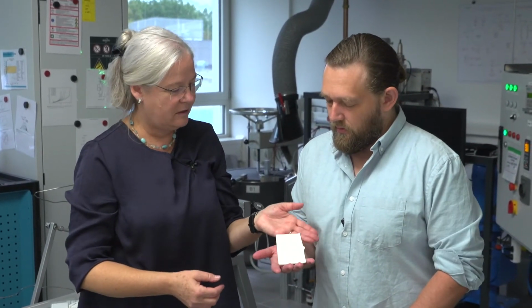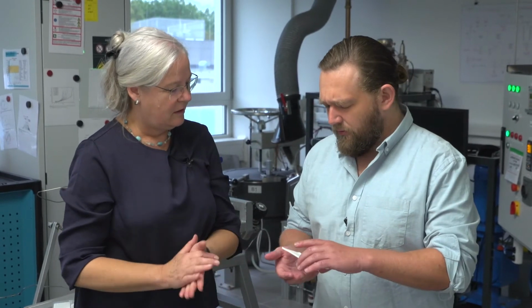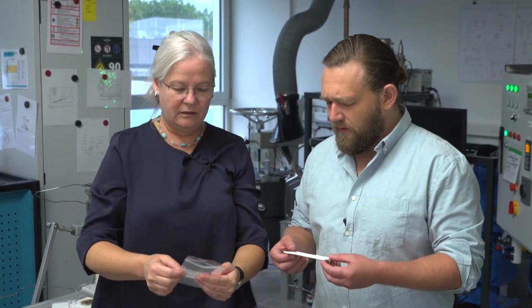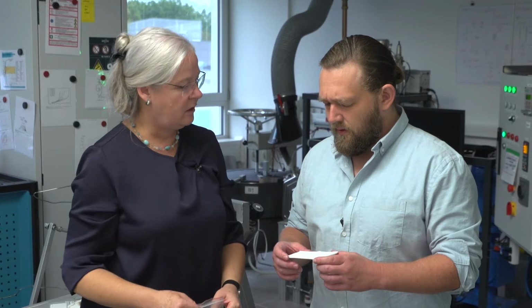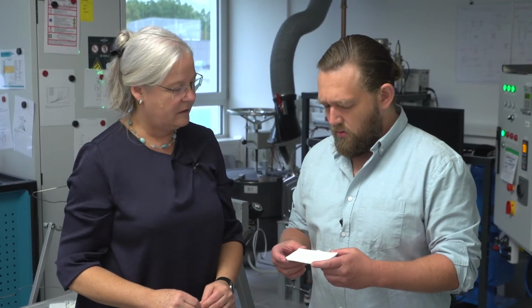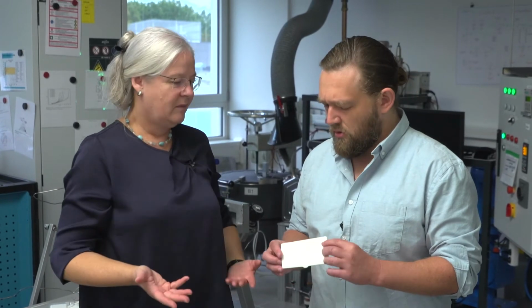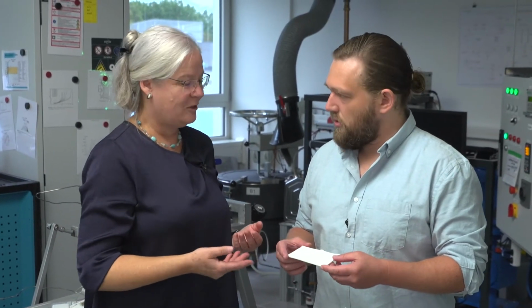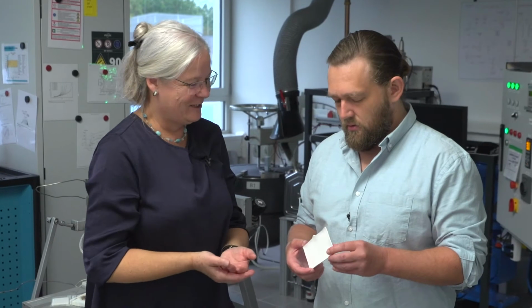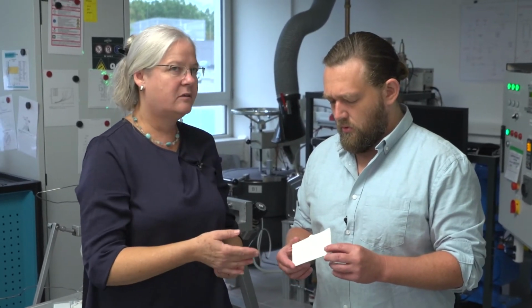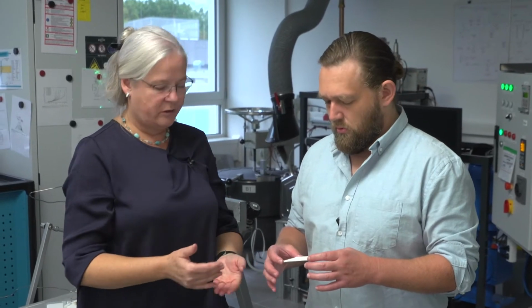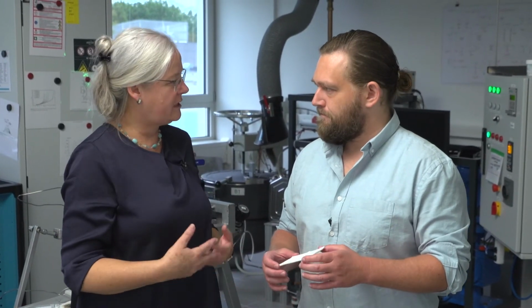Please, let's try this one. Oh, it is very light. And it is just 5-8% of cellulose. That's pretty durable, more than a normal silica aerogel. It is not dusty, and it is perfect. But it has a thermal conductivity around 30 milliwatt per meter Kelvin. We tried to get it down, but we couldn't reduce it yet with our methods.